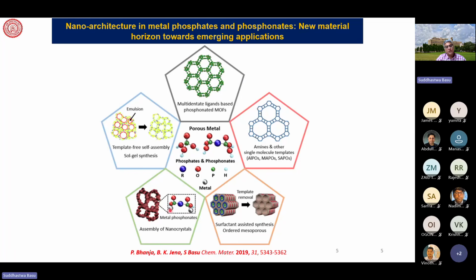And based on the structure that we have taken, which is a metal phosphonate, shown here, we make a metal phosphonate structure, in this case the one that I'm presenting, to be used for hydrogen evolution reaction and oxygen evolution reaction, which does better than the state-of-the-art material like iridium oxide, which is the standard catalyst for water splitting in a PEM electrolyzer or PEM water electrolysis cell. Okay, so that's what we will show you, and that's what we have done.